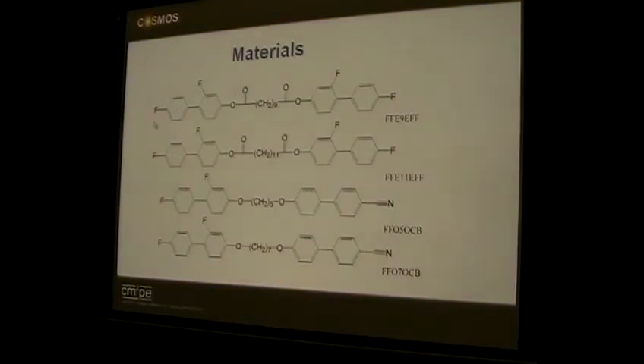Sometimes you put two on here or three on here. If I put three, then I'm going to make a much bigger dipole. But then I start losing stability of the phase, so I use that as an additive. Any materials manufacturer of liquid crystals actually plays tricks. They make a base material, like these, and then add in 5%, 10% of something with three fluorines to increase the effect. They have what they call delta epsilon, or in our case, delta epsilon over K additives. Because a trifluorinated material would only have a very narrow temperature range, but added in, it sits in the phase happily.